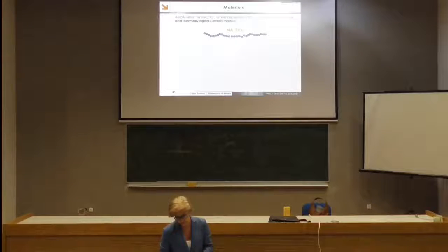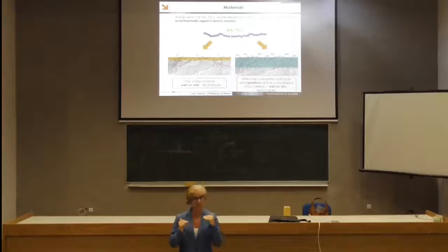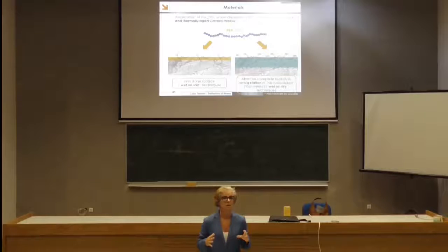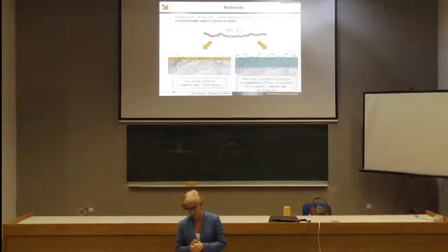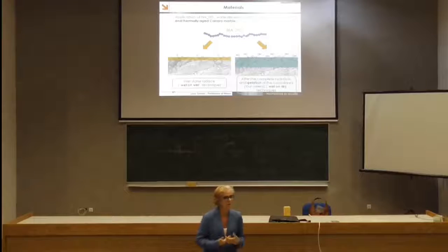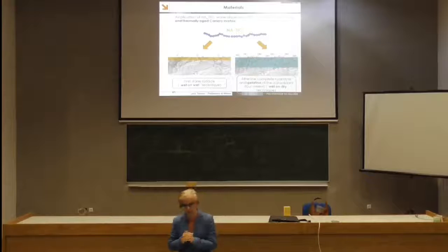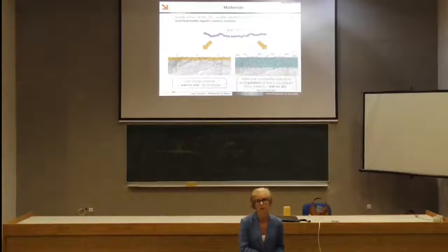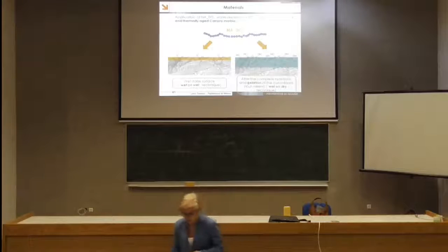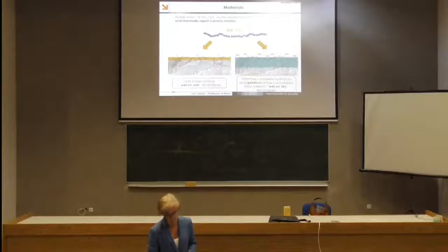And this situation, of course, proceeds in different ways according to the substrate. If the substrate is a low porous material, like marble, and we tried Carrara marble, it's a specific layer that remains on the surface, while for a porous stone, like a calcarenite, we used Noto stone, this treatment was going inside the porous structure.